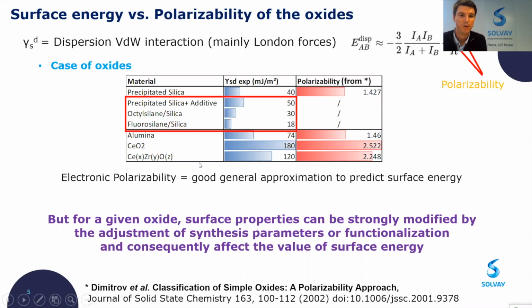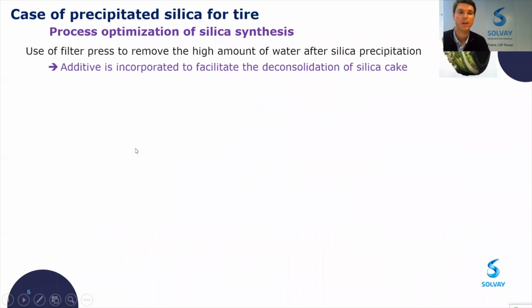And so we need to understand why. So concerning the case of precipitated silica for tire, and especially in the case of a process optimization of silica synthesis, after the precipitation of silica, we use a filter press to remove the high amount of water, and we add some additive at the surface to facilitate the deconsolidation of a silica cake.